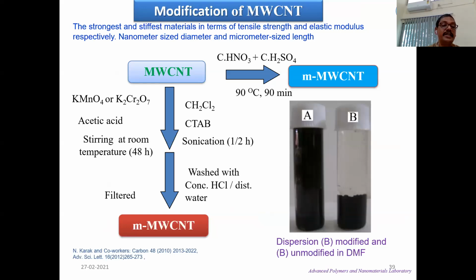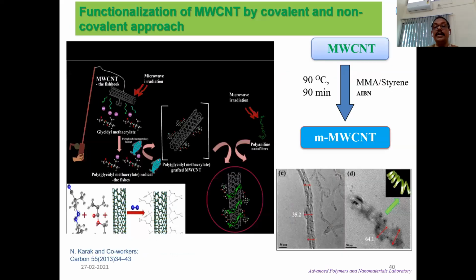However, if you use mild oxidizing agent like potassium permanganate or potassium dichromate, it's not that much detrimental, but still some loss of aspect ratio or degradation of the nanotubes happens. So in our strategy, we use a fishing approach where both covalent and non-covalent functionalization is done, so that its aspect ratio will not reduce drastically, while the functionalization remains very effective.